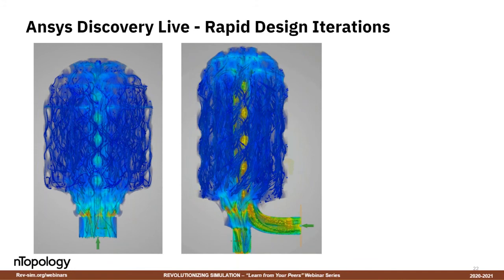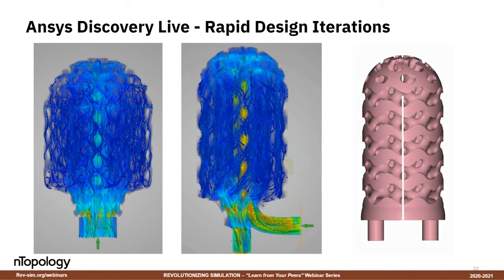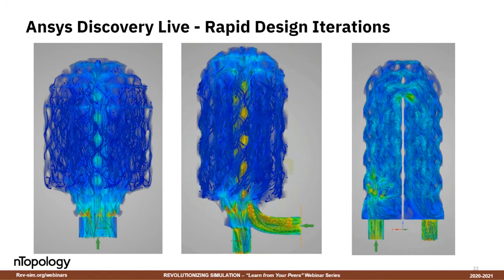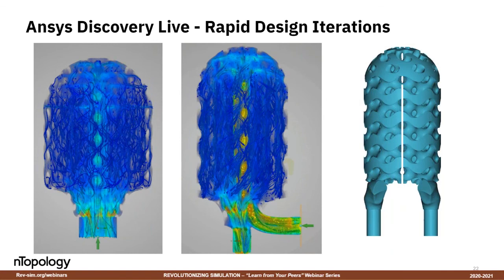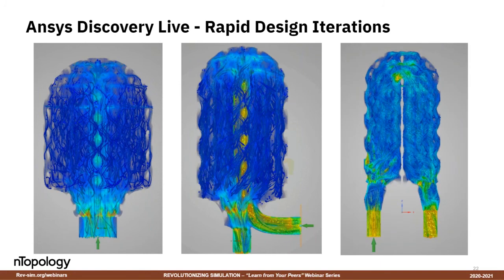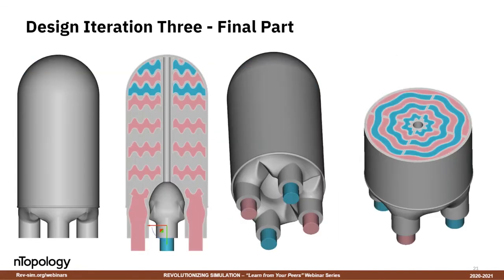The image on the left is the first cold fluid volume. The image in the center is the second. We saw relatively good flow, but when we compared it to the hot fluid flow moving through the heat exchanger, there was a significant difference, not just in the velocity of the flow, but we saw about a 55% difference in pressure drop. So we asked, is there a way that we can redesign the plumbing of the structure so that the cold domain mimics the hot domain? Ultimately we were able to figure out how to do that, and we not only improved the flow on the hot, but the cold as well. I'm going to hop back a couple slides and talk about just that for a second.